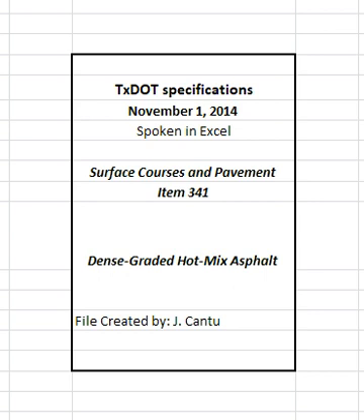4.4.1.2 Design number of gyrations, Ndesign, when the SGC is used. Design the mixture at 50 gyrations Ndesign. Use a target laboratory molded density of 96% to design the mixture, however, adjustments can be made to the end design value as noted in Table 9. The end design level may be reduced to no less than 35 gyrations at the contractor's discretion.